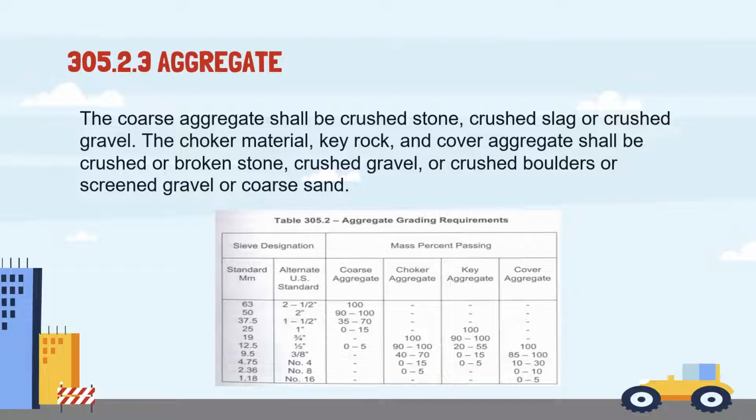Coarse aggregates are generally categorized as rock larger than the standard number, while the choker course is of 0.5-inch aggregate, and the aggregate shall have a mass percent of wear not exceeding 40. When crushed slag is used, it must be of uniform density and quality, and shall have a density not less than 1,120 kg/m³.